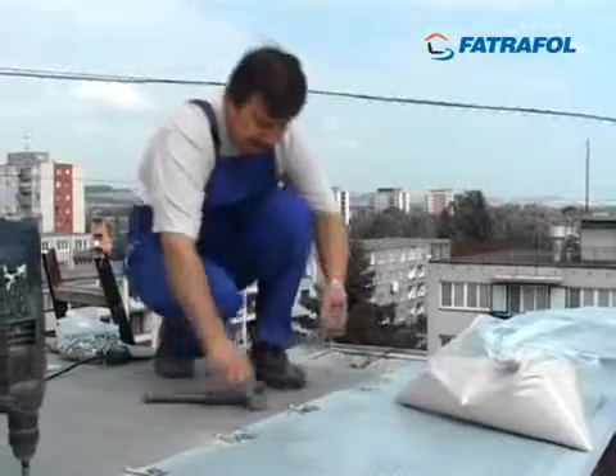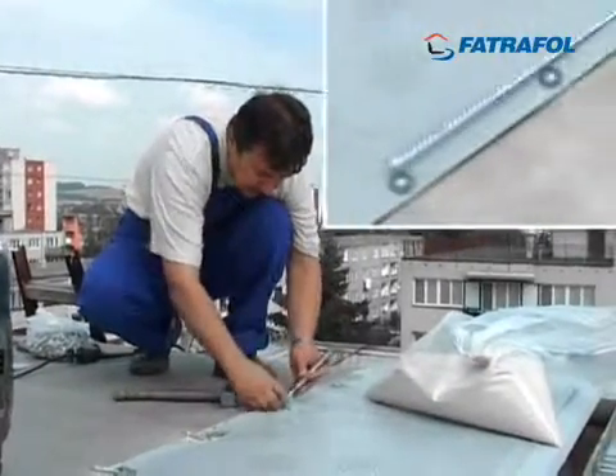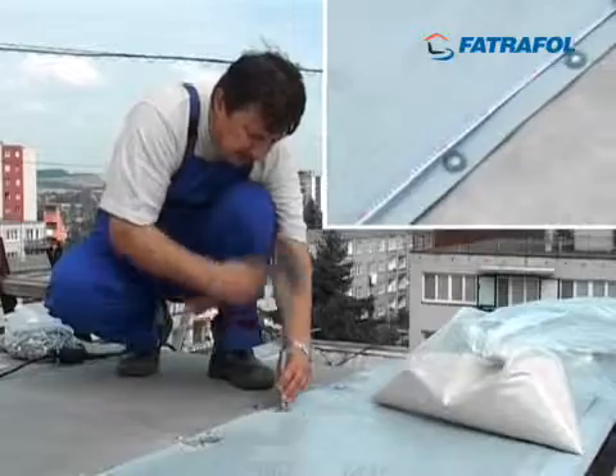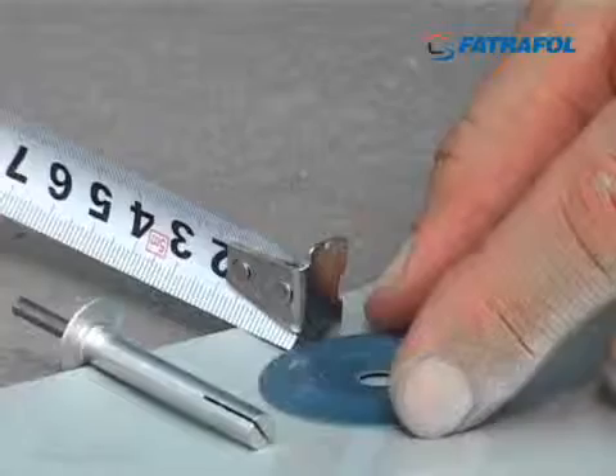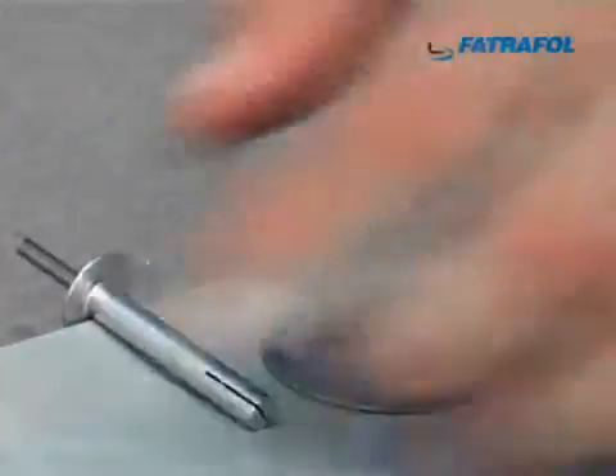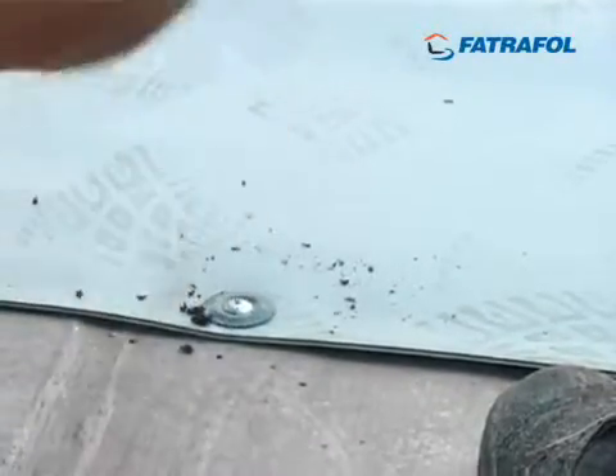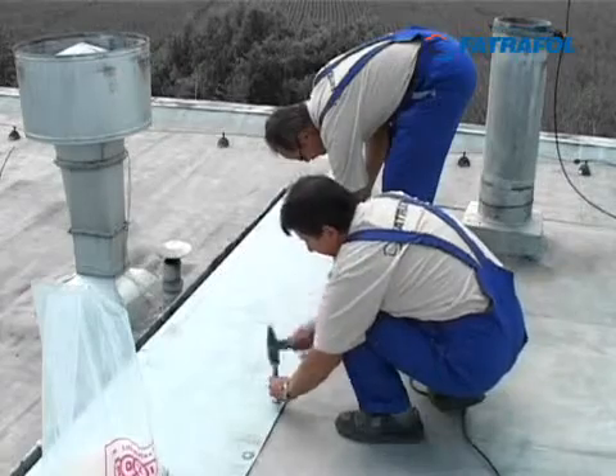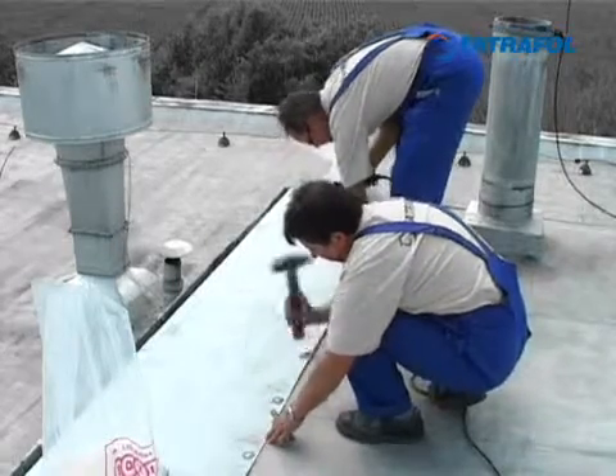Meanwhile, place fixings at 30 cm centers. Make sure that the washers are located at least 10 mm from the edge towards the band center. Measure the location of fixings along the entire band length before fixing the membrane to the base.